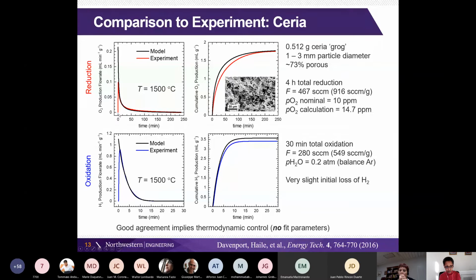We have, of course, some small time delay before we actually reach the mass spec that is detecting the gas that's evolved. Here it is on reduction. Here it is on oxidation. Similarly, the inconsistency is just in the beginning part where there are gas mixing effects and so on. But the key is to show you that this very long release time is now captured, and it's well explained by understanding the thermodynamics of this material. This tells us ceria is really very hard to reduce. That's essentially the short of it, and so therefore it takes a long time. We need a lot of sweep gas in order to get us to the equilibrium reduction state.